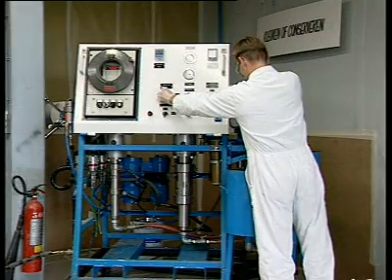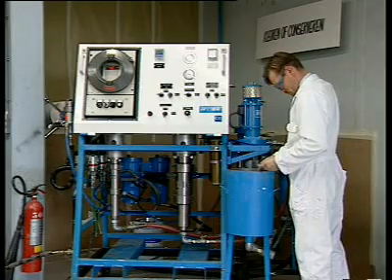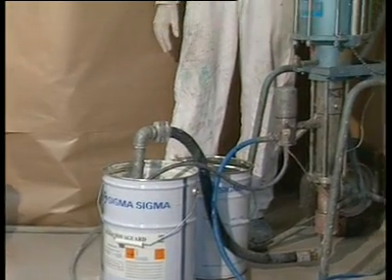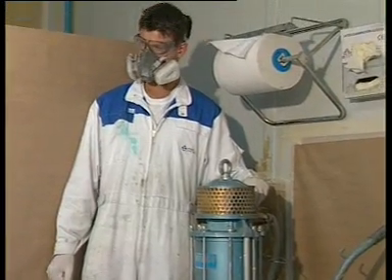There are also advantages for the applicator. The early solvent-free coatings had to be hot applied using expensive, bulky equipment. Nowadays, many of Sigma's solvent-free linings, including Novigard, can be sprayed at ambient temperature with standard 60 to 1 airless spray equipment. Novigard has remarkably long overcoating times for a solvent-free material. At 20 degrees centigrade (68 degrees Fahrenheit), it may be re-coated or repaired for a period of up to two months.